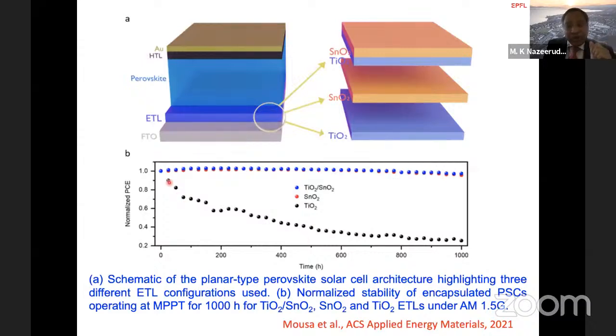So if you have a pure TiO2, the perovskite solar cell is degrading. On the contrary, if we have a pure tin oxide, the material interface seems to be extremely stable, performing up to 1000 hours. By combining tin oxide followed by TiO2, we can see that data is shown here. This is also extremely stable. So the take-home message from the ETL modifications is we do need a tin oxide perovskite interface. The moment we have a TiO2 and perovskite interface, the perovskite is not very stable.